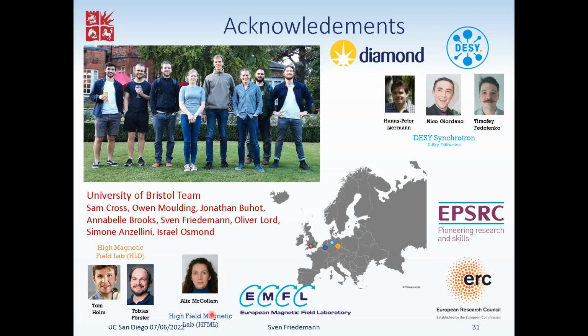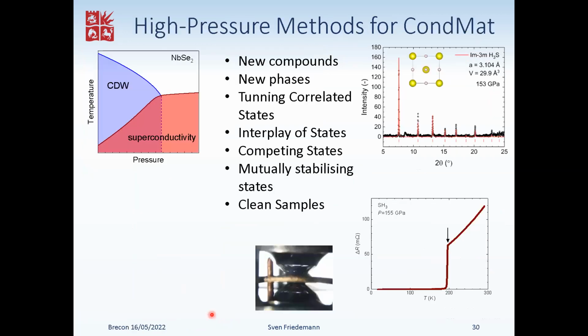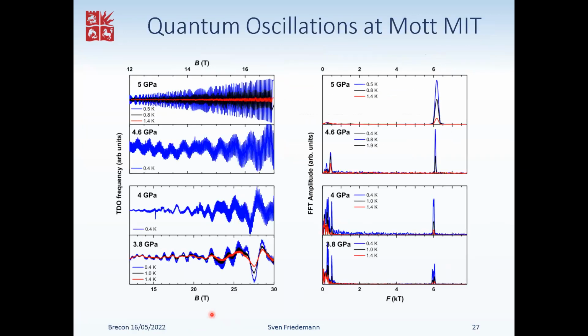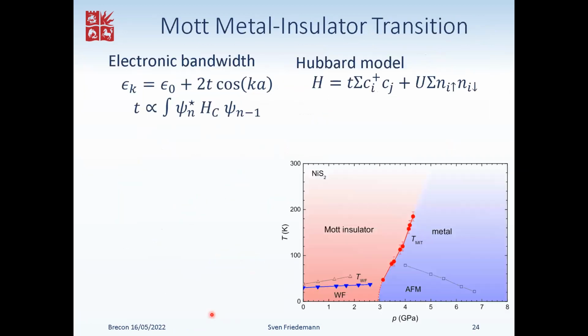Okay. Why is nickel disulfide superconducting? There's two places to hope for superconductivity, either close to the metal insulator transition, or in fact, even at the quantum critical point of the antiferromagnetism. Philip Niklowitz, who was here yesterday, has indeed done quite a long time ago transport measurements to lowest temperatures out here, did not find any superconductivity, despite the A coefficient of the resistivity having a peak there.